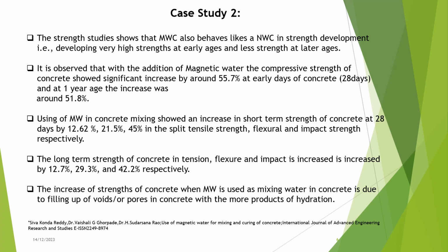Short-term strength improvement. The study observed a notable increase in short-term strength at 28 days, with improvements of 12.62%, 21.5%, and 45% in split tensile strength, flexural strength, and impact strength, respectively, when magnetized water was used in concrete mixing. Long-term strength enhancement. In the long term, concrete exhibited increased strength in tension 12.7%, flexural 29.3%, and impact 42.2% when magnetized water was used as the mixing water. This underscores the sustained positive effect on various strength parameters.